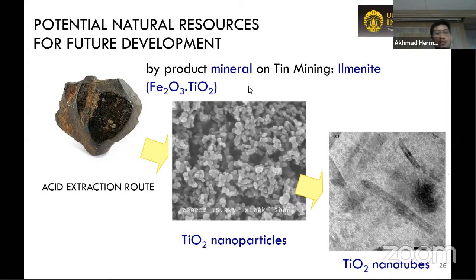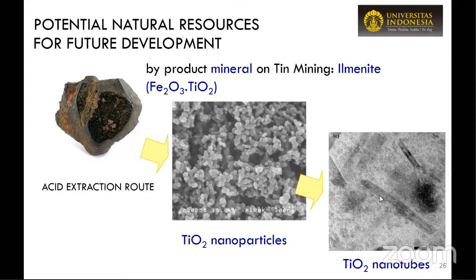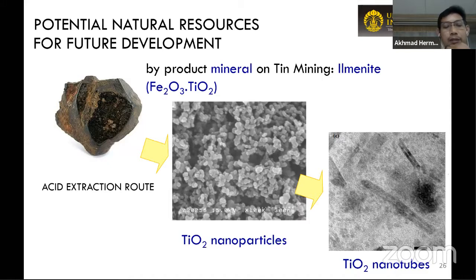I think this work has been done by the Research Center for Metallurgy and Materials, LIPI, already. How to extract ilmenite, the byproduct of tin mining, Fe2O3, TiO2, by using several methods, hydrothermal method or pyrometallurgy. So it can be extracted in order to provide titanium oxosulfate as the precursor for making TiO2 nanoparticles. This work was done by my previous PhD student, Dr. Latifa Hanum Larasari. Now she's a very active researcher in the Research Center for Metal and Materials, Dr. Agung's colleague. So this work has been obtained already: how we can extract the ilmenite, Fe2O3, TiO2, in order to form TiO2 nanoparticles.